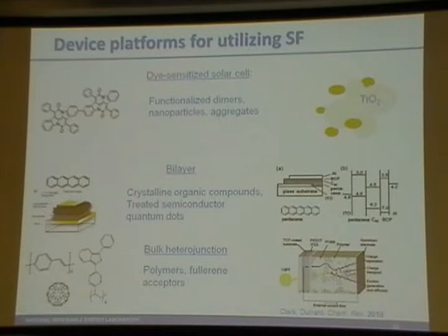Pentacene, this is tetracene. People have done tetracene and Pentacene. Essentially, what happens is mostly you excite the Pentacene, and undergo singlet fission, and they haven't shown the triplet energy level here, but it's somewhere right about where the C60 LUMO is. It injects triplets with, apparently, it's been reported, very high yield, 200%, comparing incoming photons to number of triplets being collected.